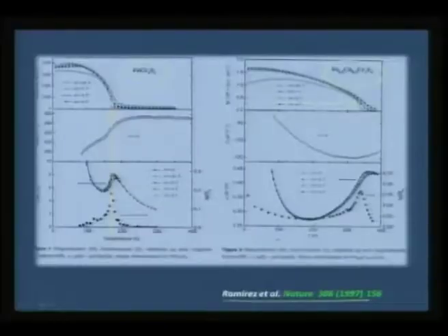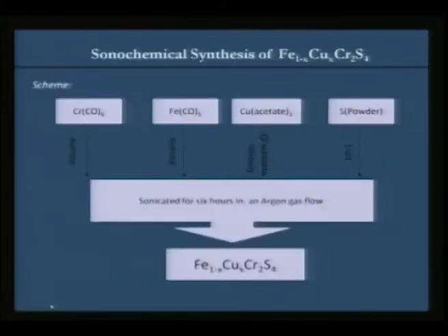Now, typically you can see there is a colossal change in the resistance in this particular composition. Therefore, this was reported to be a very good CMR, colossal magnetoresistive compound, and also because it shows Tc above room temperature, this can be explored for commercial applications. Now, having this as a motivation, if you try to attempt preparing this iron copper chromium sulfide spinel using sonochemistry, this is the protocol that one would follow.